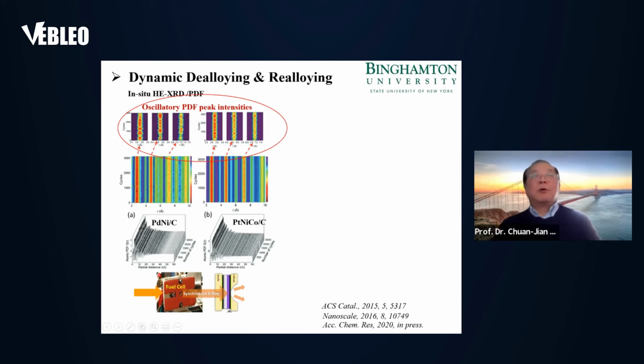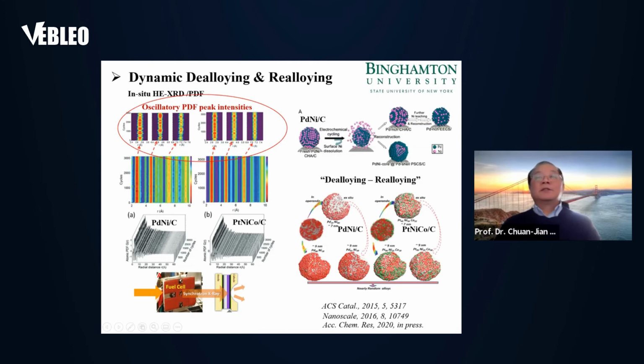This oscillation actually provides us information to understand what is going on. So what is going on? As illustrated on the right-hand side, there's basically de-alloying and re-alloying. If there's no re-alloying, they're going to form this kind of phase segregated structure, like the platinum skin, platinum shell, or platinum nickel core. And what we discovered is that because of the oscillation, because of de-alloying and re-alloying, the nanoparticle is able to restructure. That's really the key point here. And this key point is confirmed by synchrotron X-ray diffraction data because we didn't see any phase segregation. Okay, we only see alloy structure. So this oscillation really is indicative of the de-alloying and re-alloying process in the dynamic process.